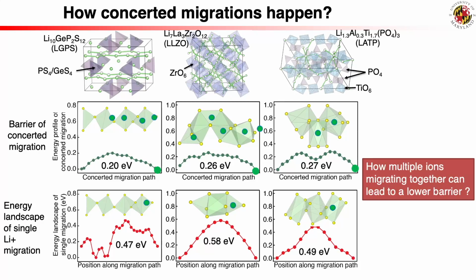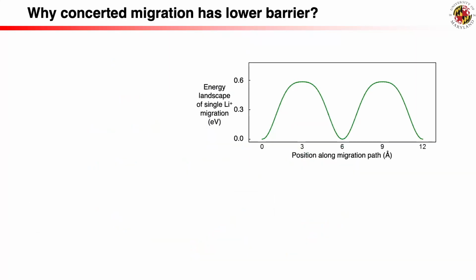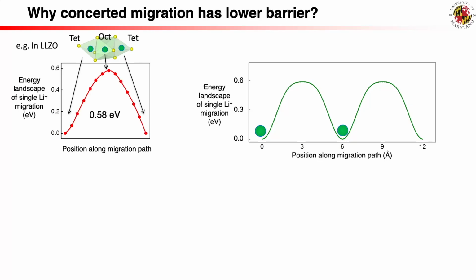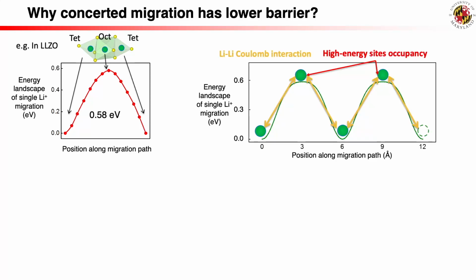Right, and the authors argue that the key is in how the ions are arranged, and how they interact with each other. Exactly. So it's not just about the individual ions. It's about the whole system, the configuration and the interactions. So what's so special about the ion arrangement in these SICs? Well, the mobile ions often occupy high energy sites. High energy, wouldn't they want to be in low energy sites? You'd think so, but at the high concentrations needed for superionic conductivity, the low energy sites are already full. So they're forced into these higher energy spots. Right, but here's the thing. The interactions between the ions actually help to stabilize them in those high energy sites. So it's not as unfavorable as it might seem at first.